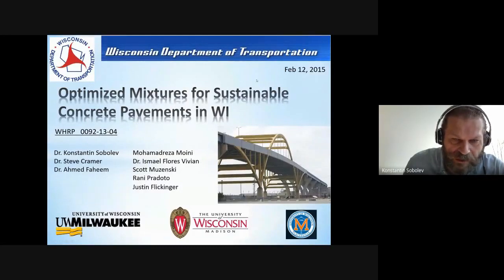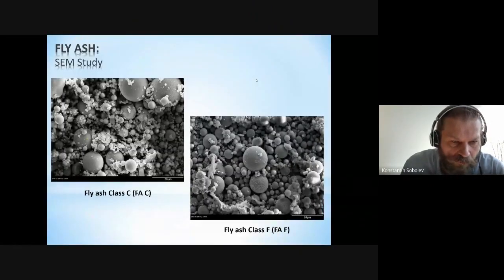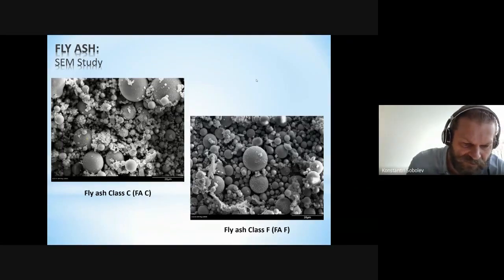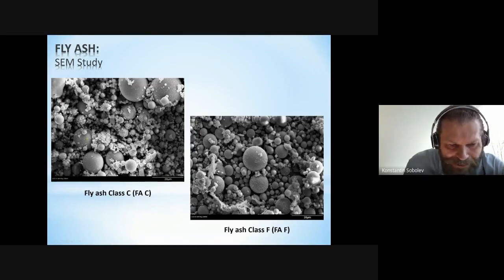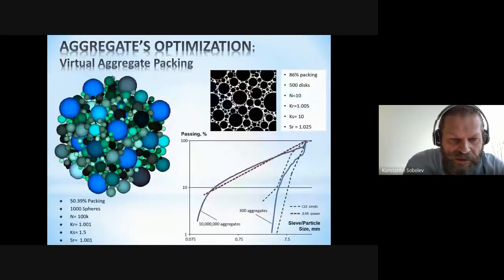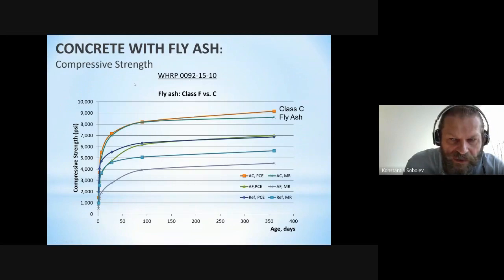We initiated a research program with the Department of Transportation here in Wisconsin, and we suggested to investigate the role of optimal concrete design. And basically, we decided to look further at the effects of fly ash and different types of fly ash, Class C and Class F. Class C is high calcium fly ash, and Class F is silicon dioxide rich fly ash. And we proposed to revisit aggregate packing and aggregate particle size distribution, so we have a better structure. And we proposed also to use modern superplasticizers to improve the performance of concrete.